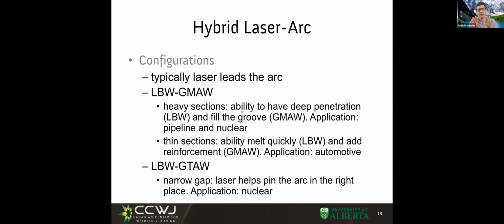Imagine you're having a butt joint and you want to use a laser. If the joint has a gap, it's very likely that the beam will go through the gap and weld your floor, but not weld your plate. So if you combine it with MIG, MIG closes the gap, and even if the laser is leading the arc, the laser is aiming at the weld pool, and that gives you the absorption of the heat by the weld pool.